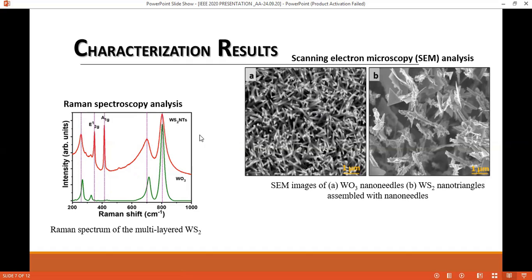Then from Raman spectroscopy, two spectra were observed. In the lower spectrum, all the peaks indicate the formation of the monoclinic tungsten trioxide phase, whereas in the upper spectrum, the two main Raman active modes for 2H tungsten disulfide at 348 and 414 were found. In addition, two broad peaks at 700 and 803 were also detected with a low intensity compared to the tungsten disulfide spectrum, indicating the presence of some tungsten trioxide impurities.